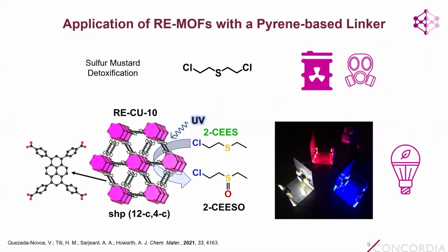And so the reason that we're interested in making MOFs with these pyrene-based linkers is because we want to use the pyrene linkers as photosensitizers to generate singlet oxygen, and then to use that singlet oxygen to go on and selectively oxidize and detoxify mustard gas. Now, specifically, we don't use the sulfur mustard compound in our lab. We use this simulant here called 2-chloroethyl ethyl sulfide, which is safer to use, easier to handle, and has very similar reactivity to the real chemical warfare agent.